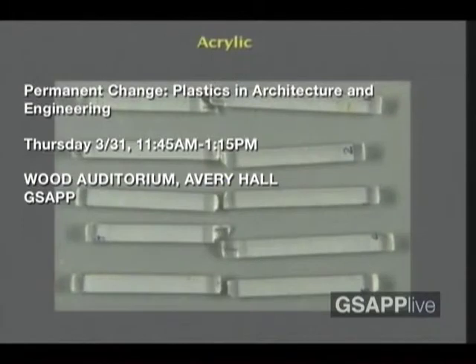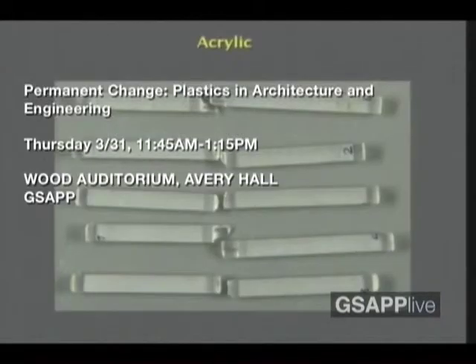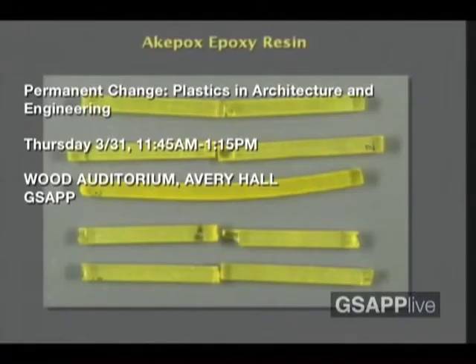And just to look at some of the plastics themselves, unreinforced with fibers, they are brittle materials. They're not very stiff materials. This is a very, very low flexure modulus, but boom, they break, they snap at the end. So just using a plastic pin by itself is not a good idea, both because of the low modulus and the brittle failure. Those are acrylics. Here's epoxy resins. By the way, that was a thermoplastic material. This is a thermosetting material that we just heard from Lydia.